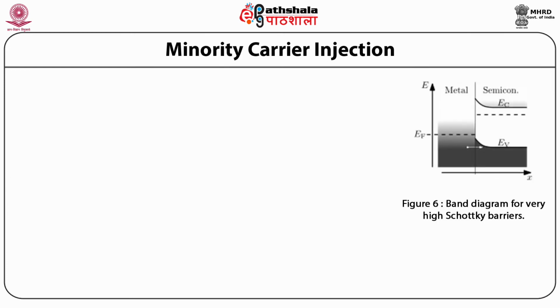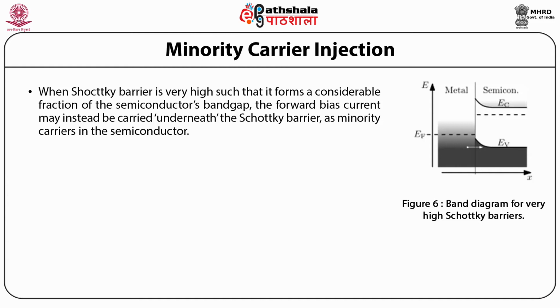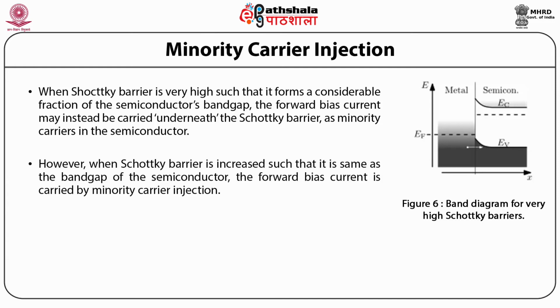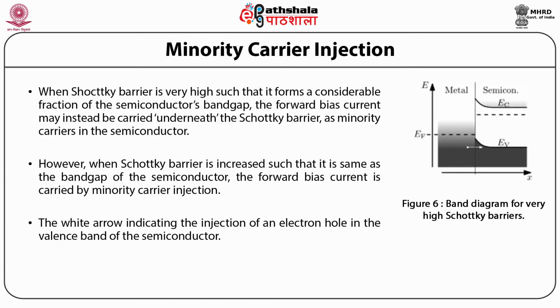Minority carrier injection. When the Schottky barrier is very high, such that it forms a considerable fraction of the semiconductor's band gap, the forward bias current may instead be carried underneath the Schottky barrier as minority carriers in the semiconductor. However, when the Schottky barrier is increased such that it is the same as the band gap of the semiconductor, the forward bias current is carried by minority carrier injection. This is shown in figure 6 with the white arrow indicating the injection of an electron hole in the valence band of the semiconductor.